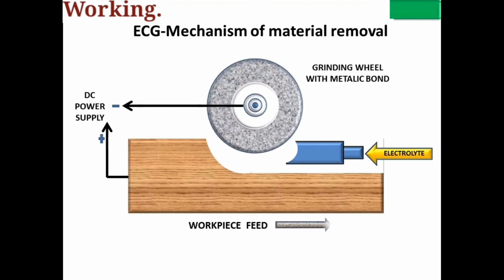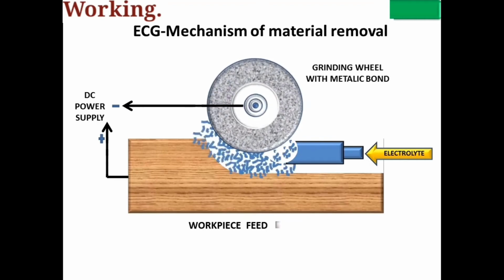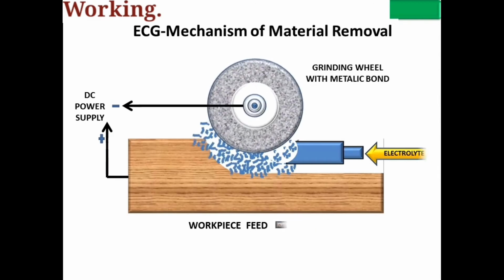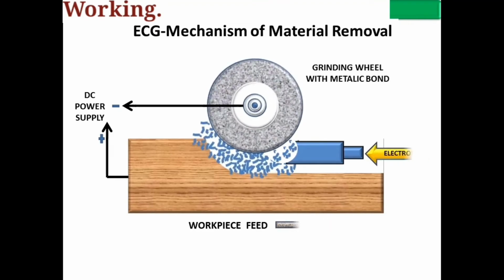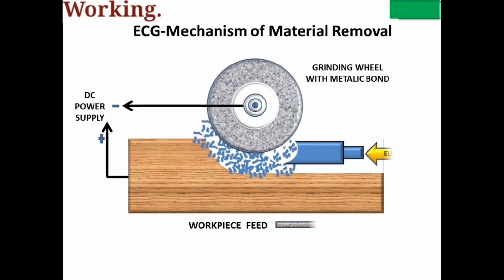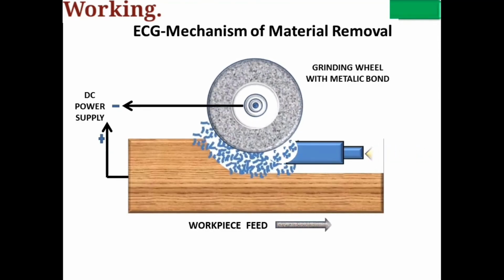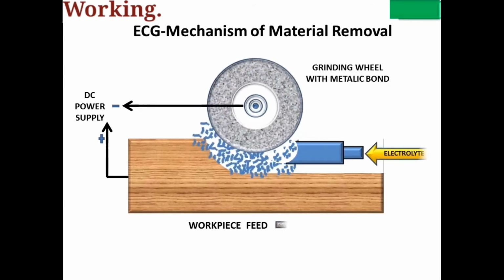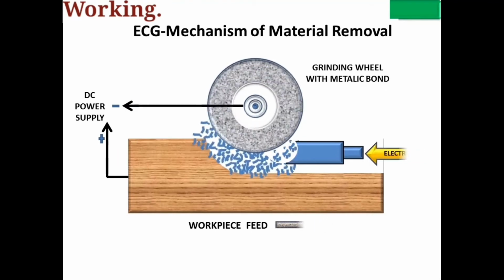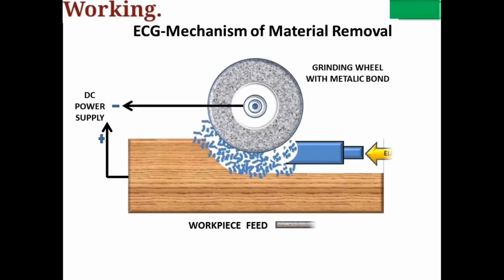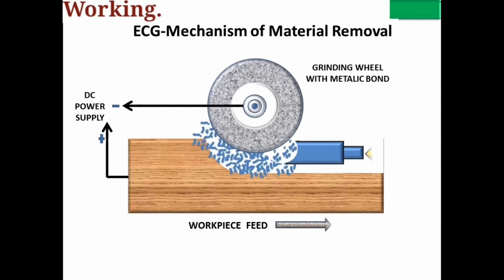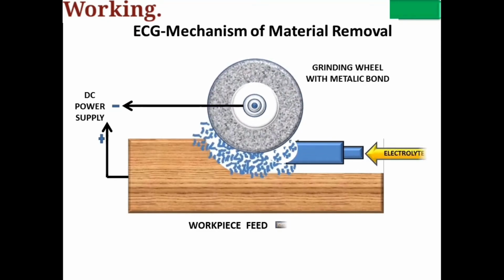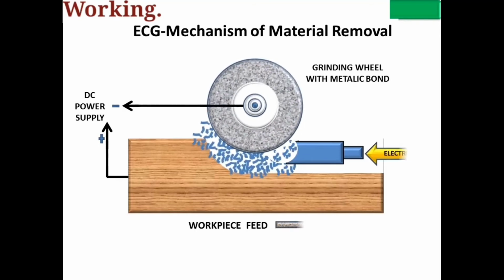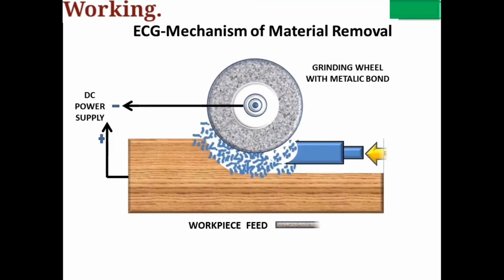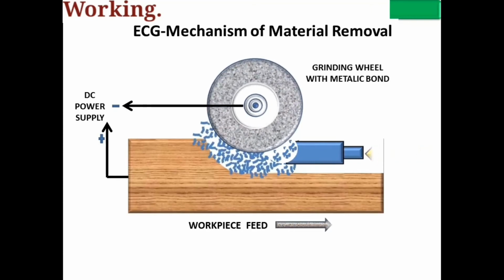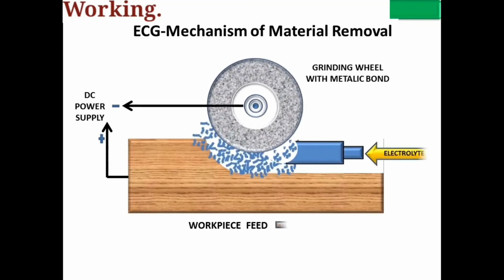The electrolyte is fed through the constant inter-electrode gap. The grinding wheel is given a certain speed in RPM and the electrolyte is present between the tool and workpiece. First, the reduction in IEG results in the contacting of abrasive particles with the workpiece, and material is also removed by the abrasive action. With the help of the abrasive particles, material is removed in the form of chips, and the non-reactive oxide layer is also removed, which promotes more electrolytic dissolution. In this process, the major material removal takes place by electrolytic action, which is around 90%, and the remaining around 10% takes place due to the mechanical grinding action.